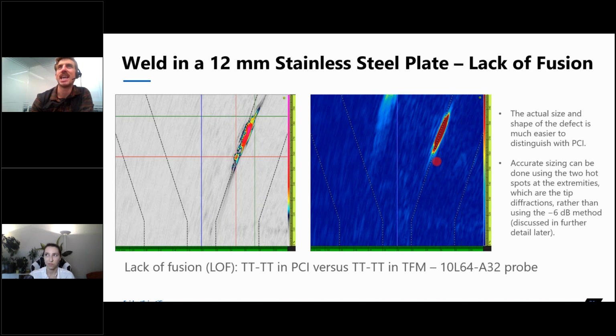If we increase the gain quite a bit, we can see them a bit. We can start to see them a bit more with regular TFM, but with PCI, we can see the reflection from the surface of our lack of fusion and then the two tips at either extremity. And that's making sizing of these kinds of defects a lot easier, because we can just place our cursors directly on the ends, which are highlighted by the technique, rather than having to establish our gain at a reference and doing a -6 dB drop in order to find the size of our lack of fusion. But as far as how sizing can be easier using PCI, we're going to talk about it in depth a bit later.